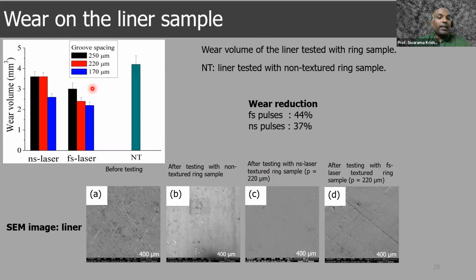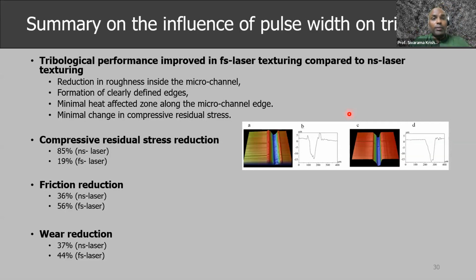We found that for groove spacings of about 170 micrometers, the wear volume on the liner of these pistons is significantly smaller in the case of femtosecond pulses. Nanosecond pulses don't perform too badly. Nonetheless, as compared to the non-textured material, the textured material performs way better. But the wear reduction is much better in the case of femtosecond pulses.